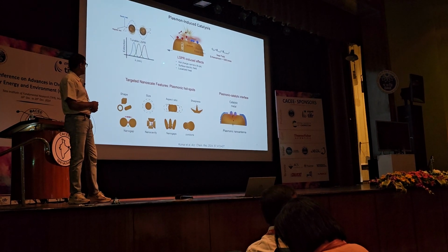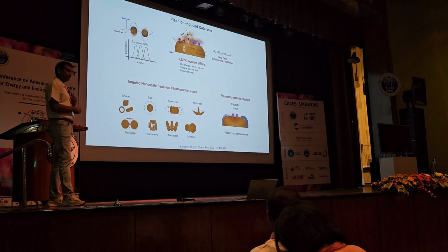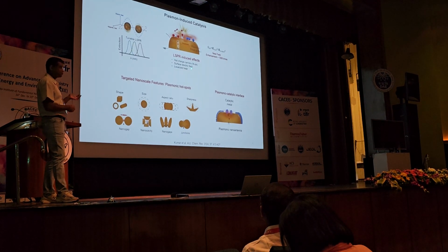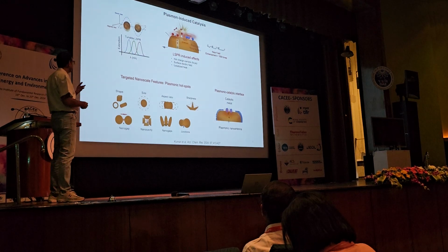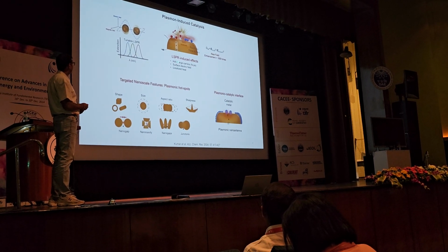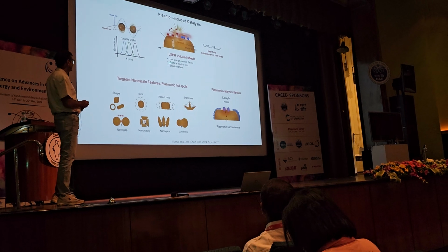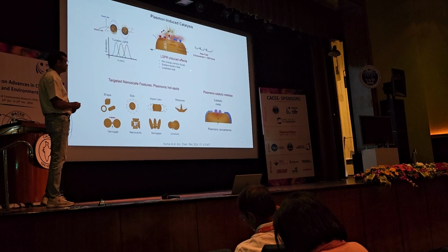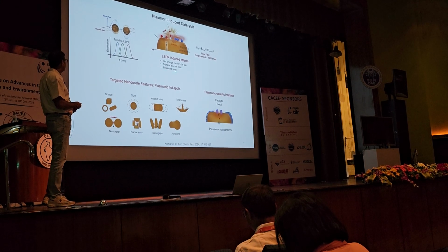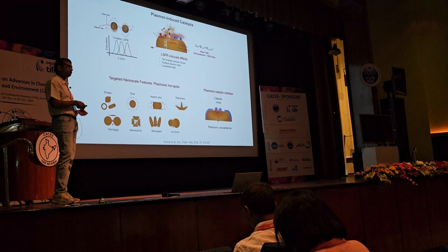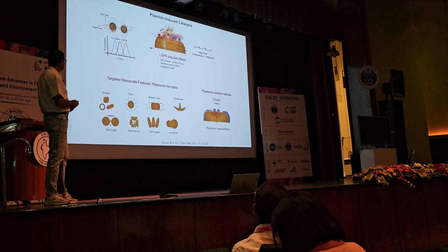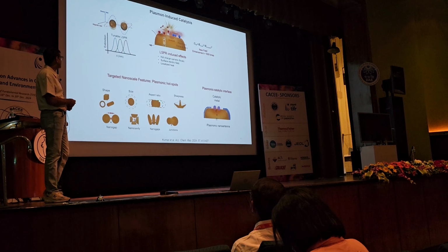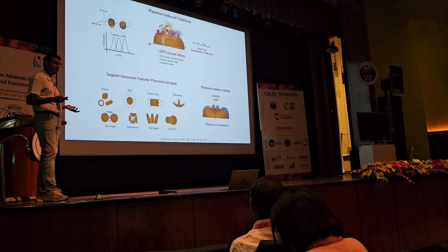In terms of mechanisms, although we don't work very extensively on figuring out how different effects participate in these reactions, Professor Vivek has created a lot of knowledge on this side. There could be participation of hot charge carriers, which can be produced within the time scale of femtoseconds to picoseconds, and then the surface electric field and localized heat. So there is an intricate effect of all these factors. Interestingly, all these features can be controlled by controlling shape, size, aspect ratio, sharpness, and many intricate nanostructural features